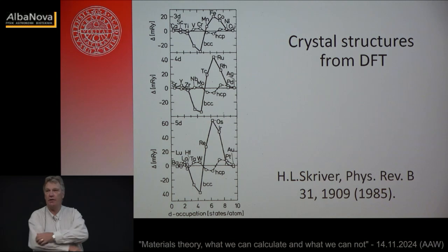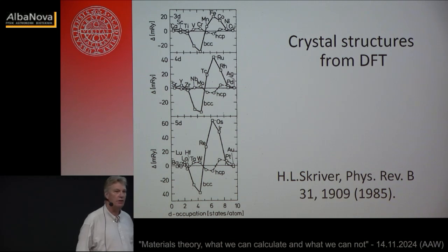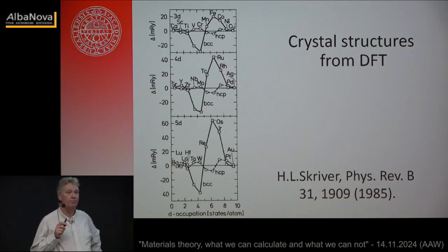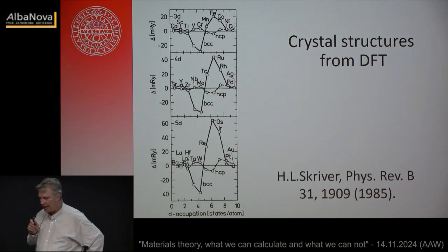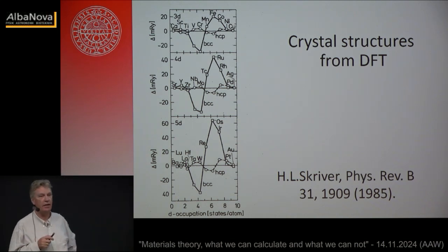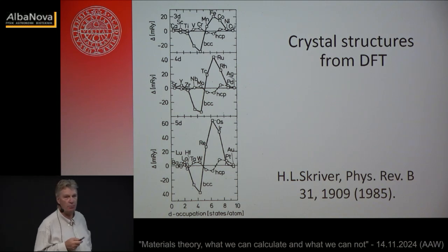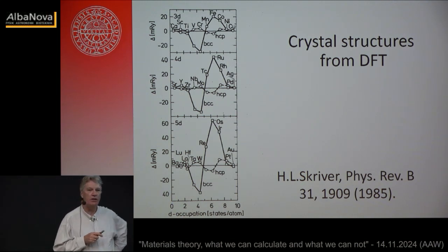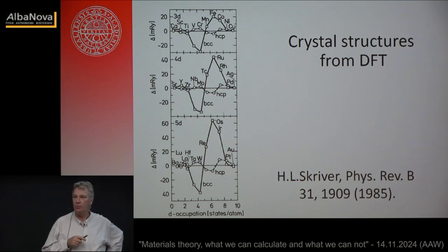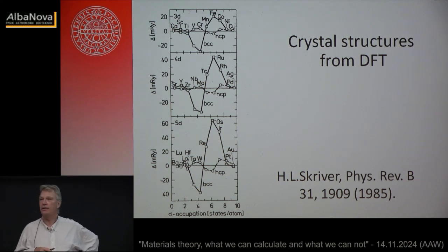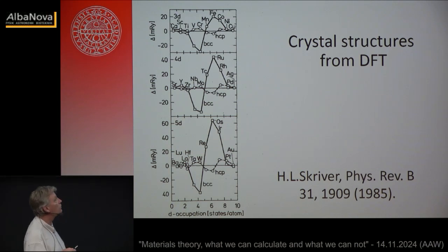So when I started out my PhD work, it was not so obvious what we could do and could not do. And one of the landmark things that Hans Skriver could demonstrate was that it's possible. There's enough accuracy in this approach to calculate rather fine details, for instance, as described by the crystal structure stability. And there are certain trends that are very clear and obvious across the periodic table. And Hans Skriver wrote a paper where he analyzed the structural stability of basically all elements of the periodic table, and he could reproduce the experimentally determined structure, with one exception: gold. Gold, what he found, was supposed to be BCC in this work, and it's of course FCC.